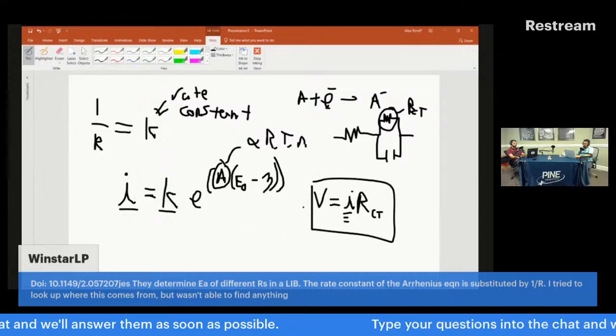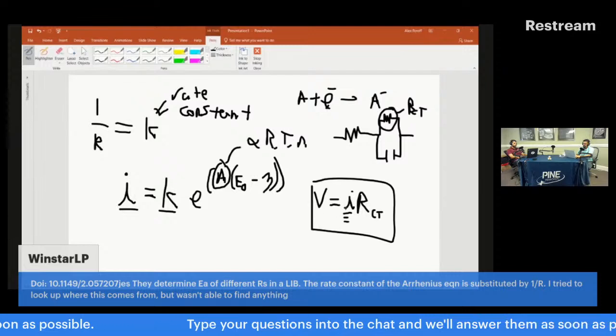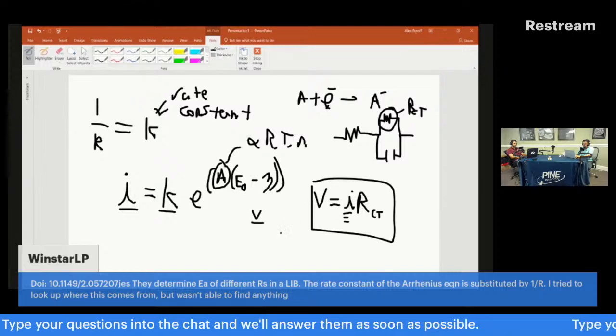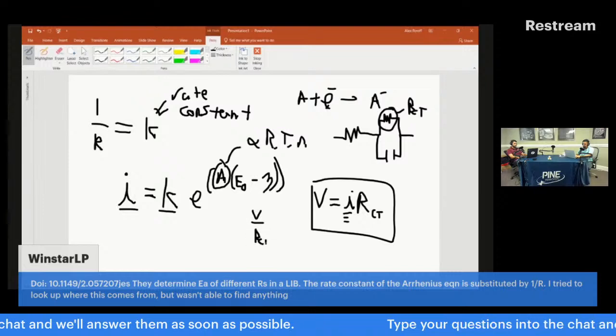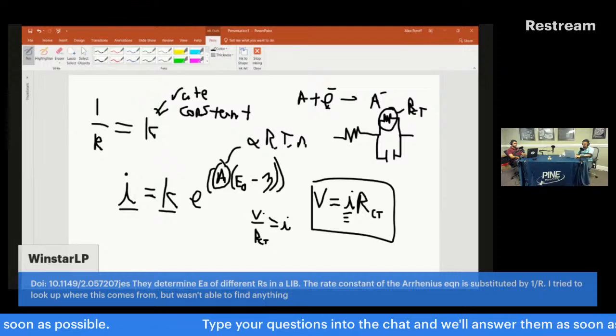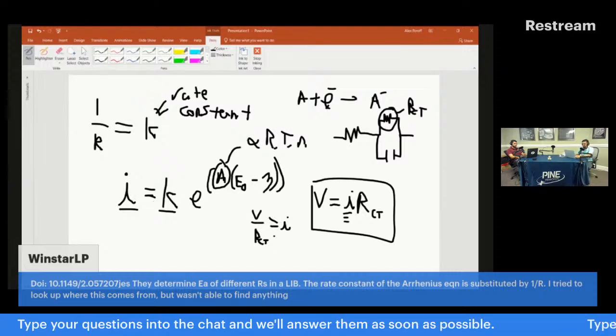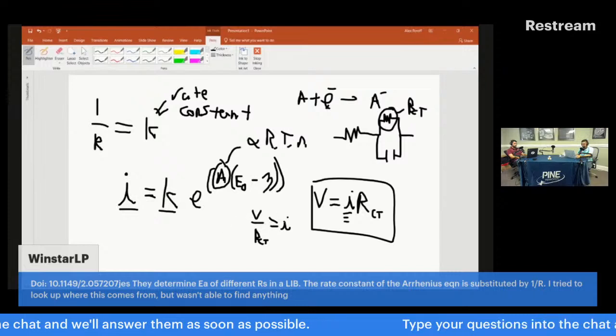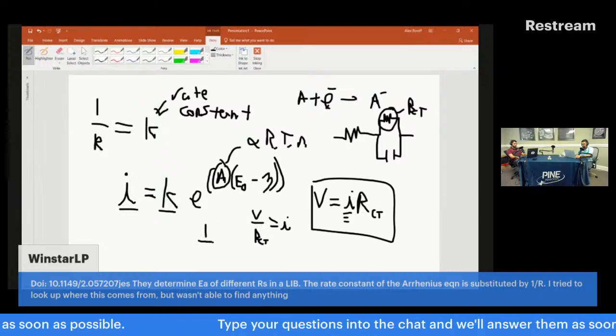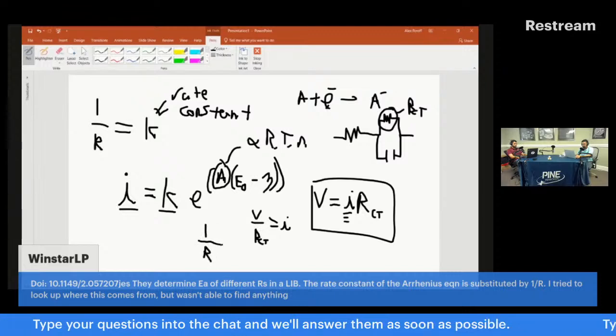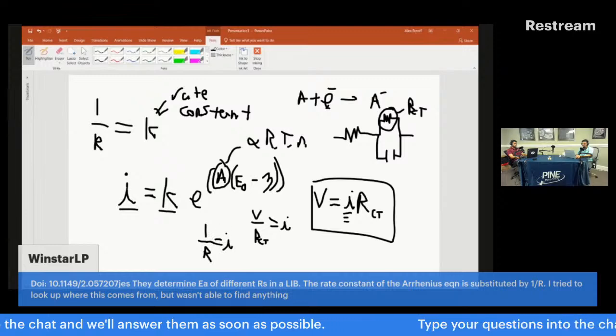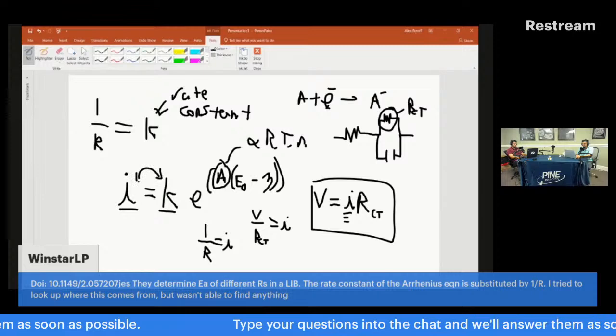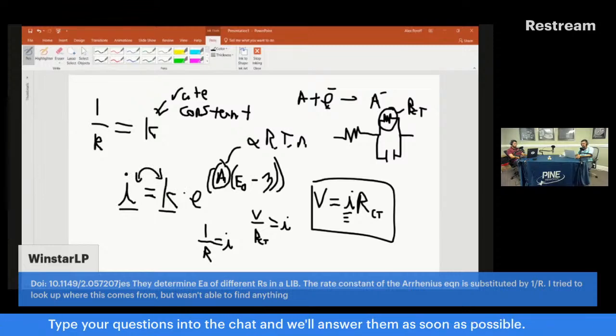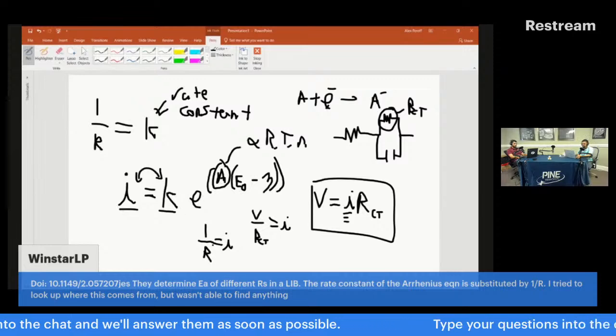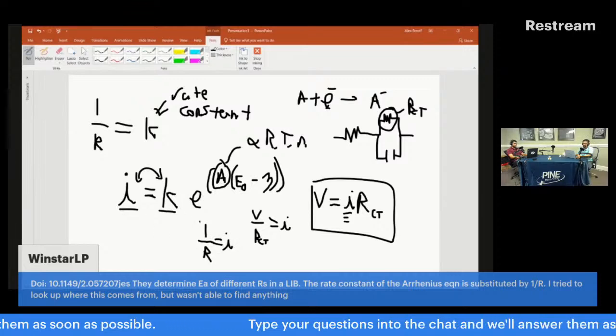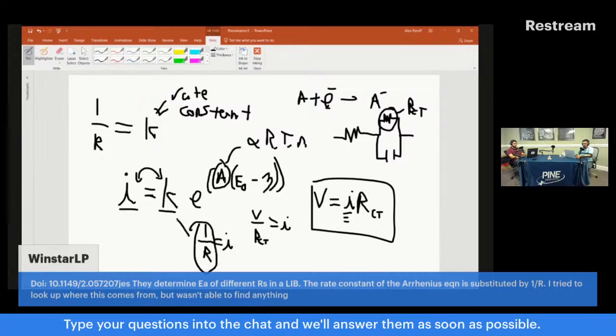So if we look at it this way, if we solve for I, we know that the voltage over RCT is equal to I. And the voltage in these experiments with doing EIS, let's say the voltage is more or less constant. We now have a way of looking at this inverse relationship between 1 over R and the current. And because the current has a direct proportionality to the rate constant at a specific potential, then we can in a way substitute this 1 over R for k.